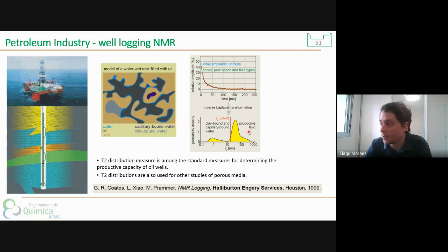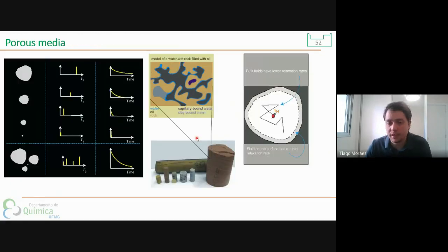They do this kind of analysis with the T2 spectra that I will explain in a few minutes. To understand the T2 spectra, let's first understand that oil and water can have different relaxation times, of course, because they are different chemical components. This is easy to understand. But also, water alone can have different relaxation times. For example, if you think of water molecules inside a pore, depending on the mobility of the molecule, it will have different correlation times, and this will be reflected in the relaxation times.